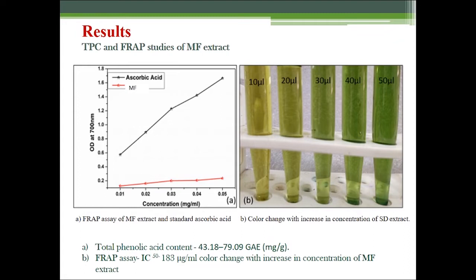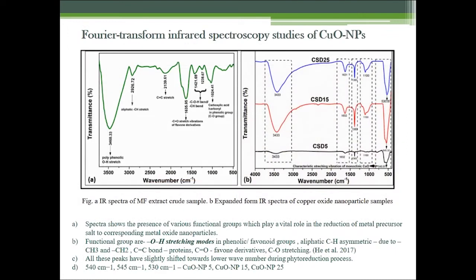Once the nanoparticles were synthesized, characterization was done. The first characterization technique was FTIR analysis. Here we have two graphs. This graph represents the IR spectra of Mussaenda frondosa crude extract, and this is the expanded form of IR spectra of copper oxide nanoparticles. This gives you the comparative analysis of the FTIR spectra of the plant extract as well as the nanoparticles synthesized from that extract.